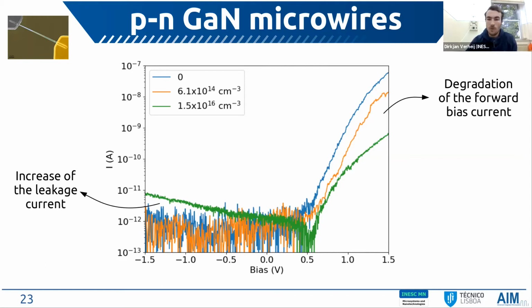So here I show in blue the original IV curve, and we see that for a fluence of around 6 × 10¹⁴ protons per square centimeter, we do not see any increase in the leakage current, but only a degradation of the forward bias current. And this degradation continues when increasing the fluence. But at higher fluence, we finally also see some increase of the leakage current. However, this increase in the leakage current is actually relatively low when compared with devices in other literature.